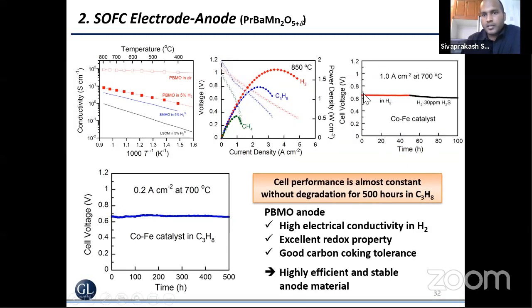This shows the performance of praseodymium barium manganese oxide. In hydrogen, it shows very stable performance. But when switching the fuel from hydrogen to 30 ppm sulfur containing fuel, it's still stable. No substantial degradation is observed, though 1% degradation is allowed in fuel cell technology.